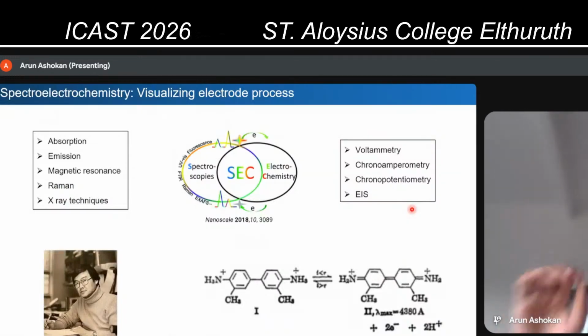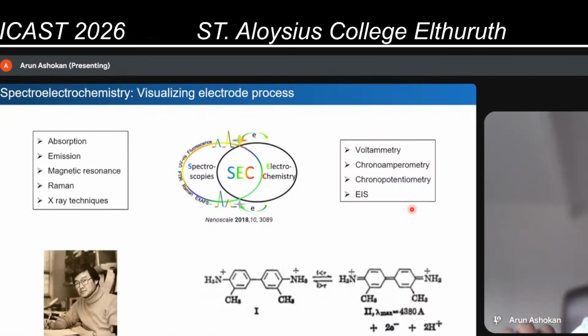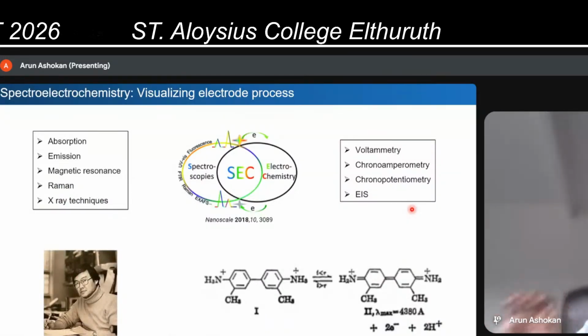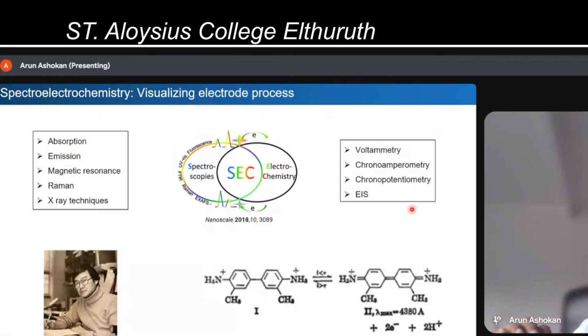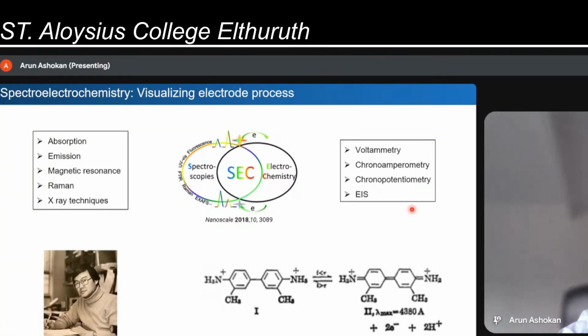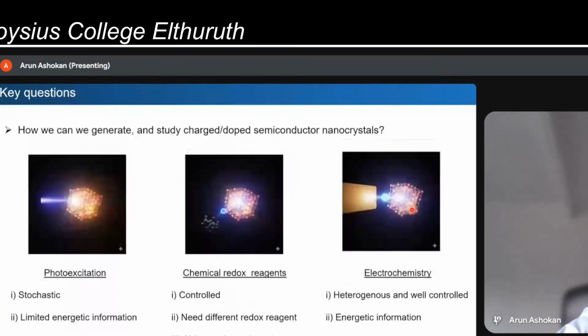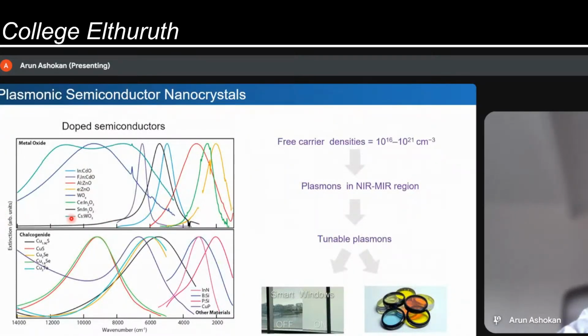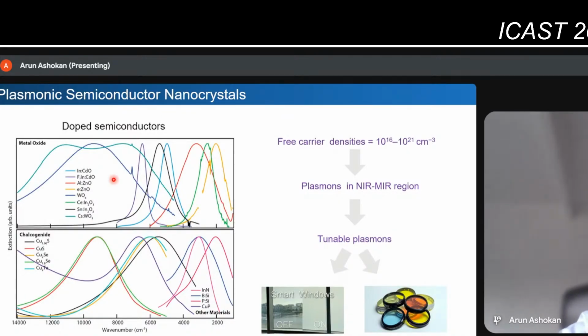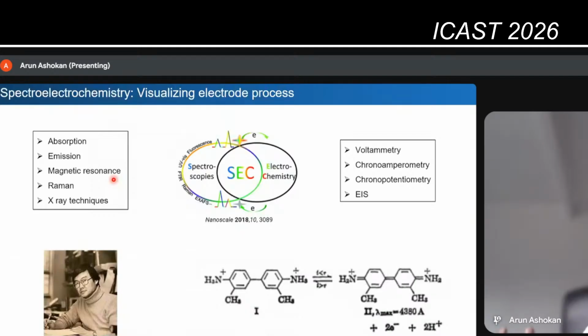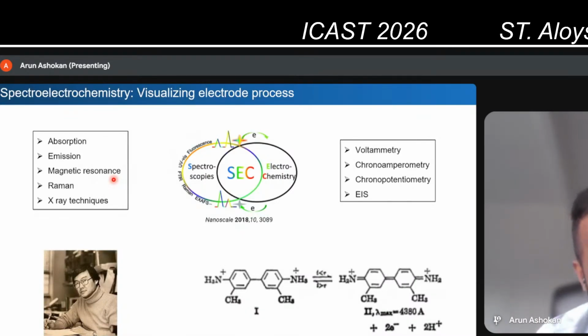So when you charge these nanocrystals, you're charging them, but at the same time, we want to observe the plasmon. So what we want to do is combine a spectroscopic method. You can see here that these are plasmonic peaks. If you want to see some shift in these plasmonic peaks, we need to simultaneously do spectroscopy. This technique of combining electrochemistry and spectroscopy is called spectroelectrochemistry.